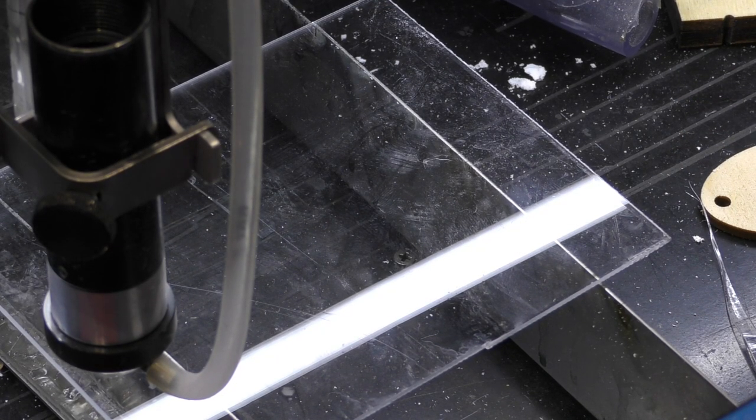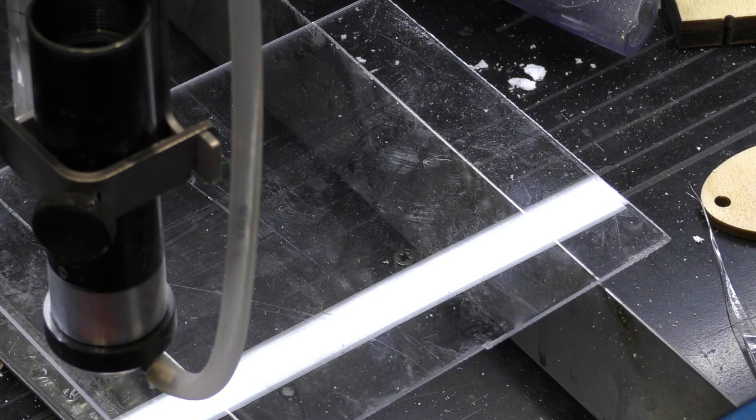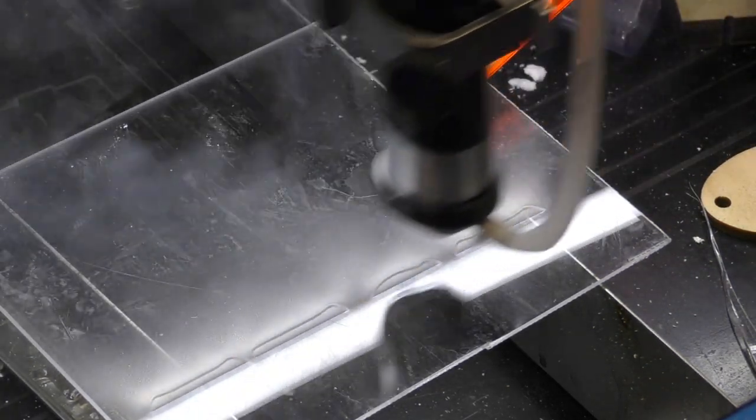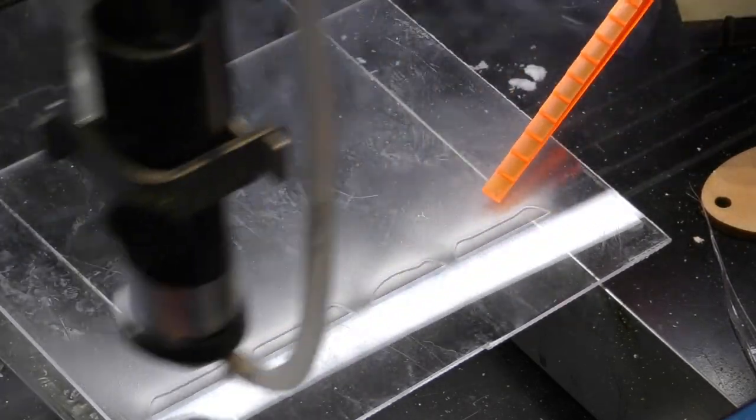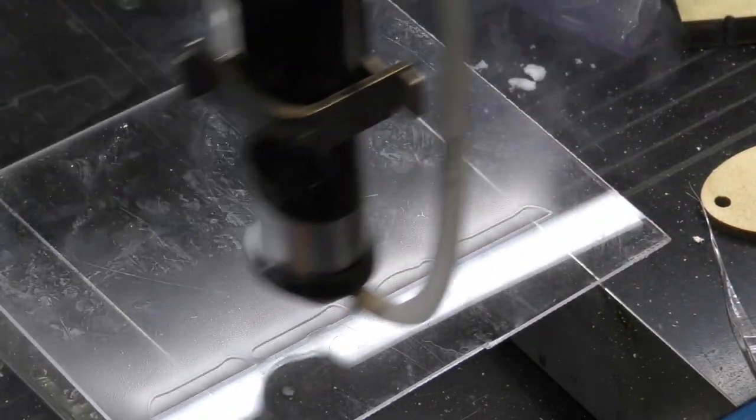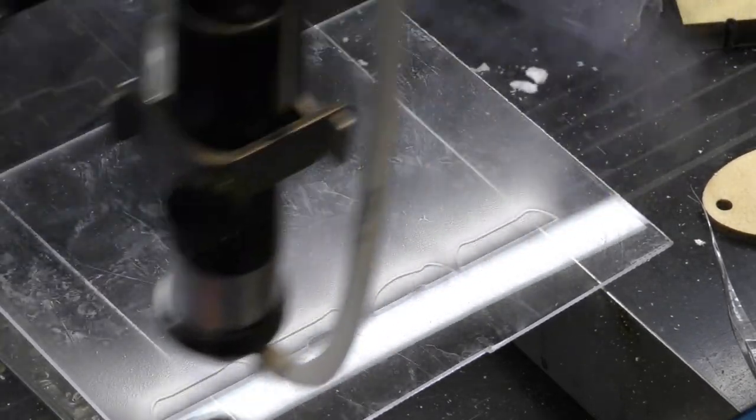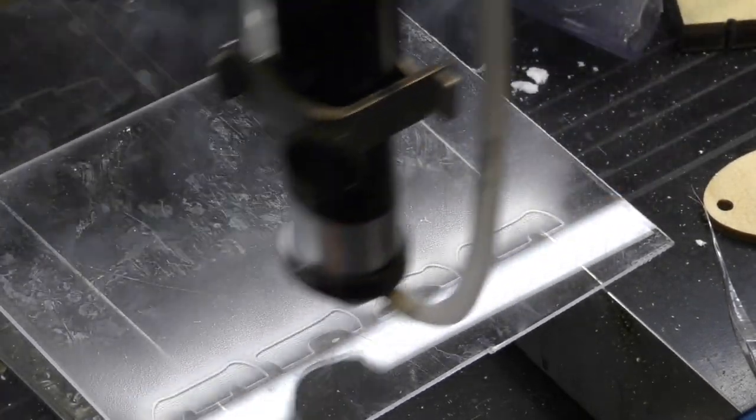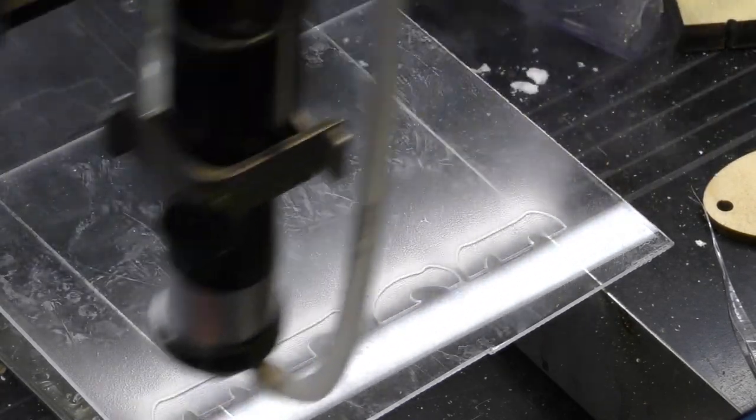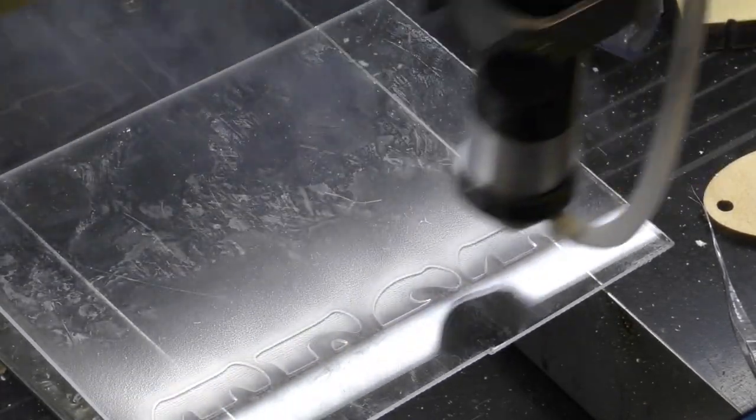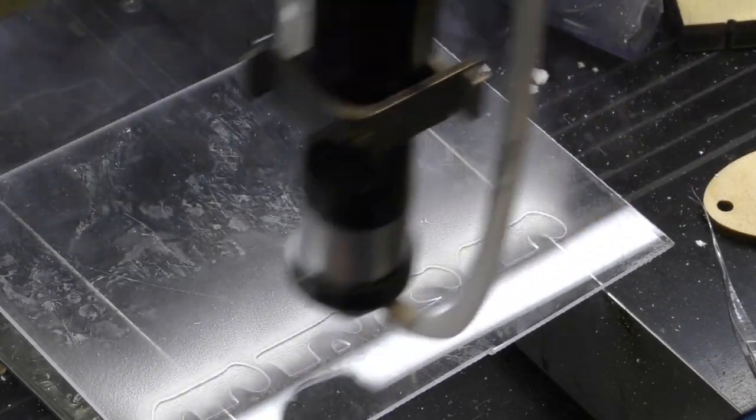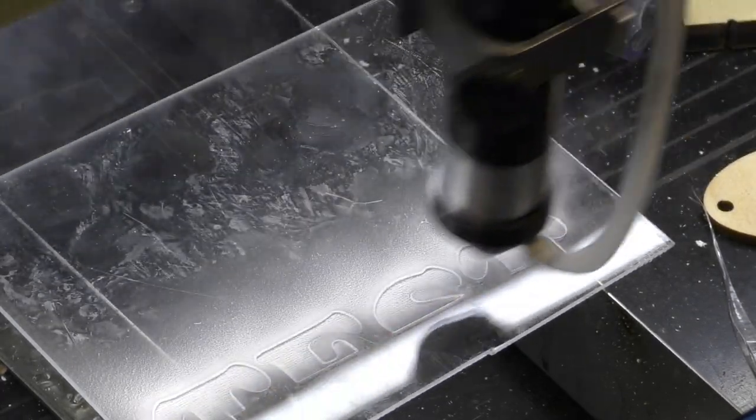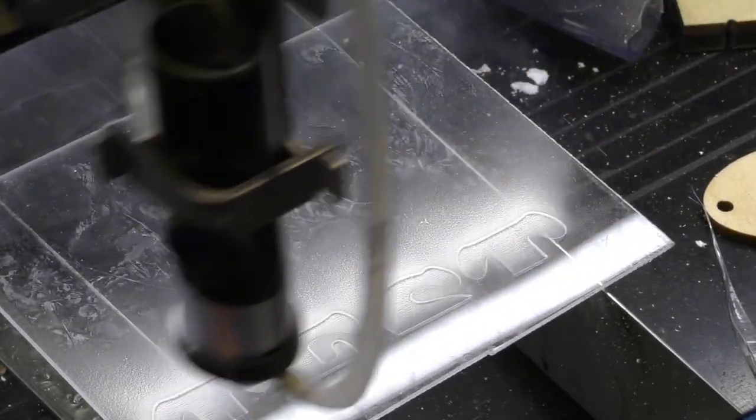Okay, so let's try my normal black file. So this is 70 watts at 400 millimeters a second, which would be normal-ish for most machines. You can already see the condensation building up here. Because we're modifying so much material and converting it into vapor. We've got a cut there that might be half a millimeter deep. So that's a lot of material that we're actually converting into vapor.